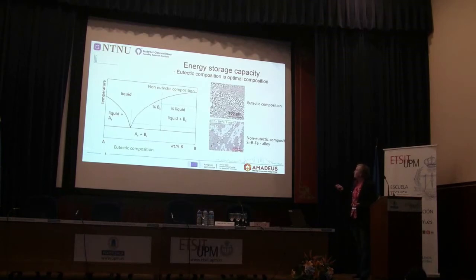So if we look at the eutectic composition, it will typically look like this, where you have a very intermediate structure after it's solidified down here. However, if you're at a non-eutectic composition, it will be like this, where we have a lot of eutectic structure here, but we will have some primary crystallization that has been precipitated here. So actually what we see in the silicon-boron alloy that we have investigated is that it may not follow the thermodynamic databases, or that the thermodynamic databases are not accurate, so we are really not at a eutectic level. So we have to continue to work on that to find the eutectic composition actually.